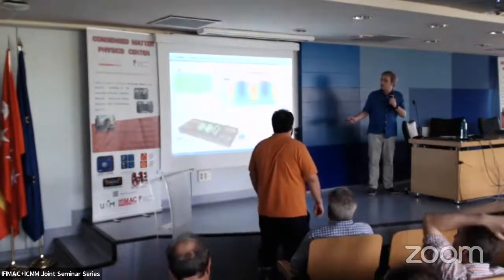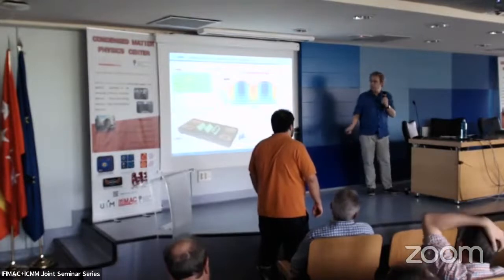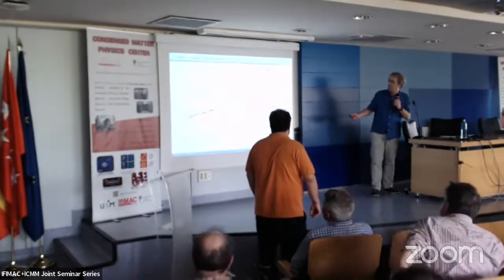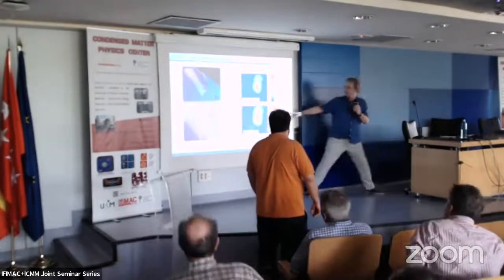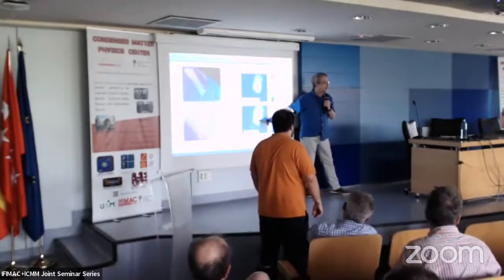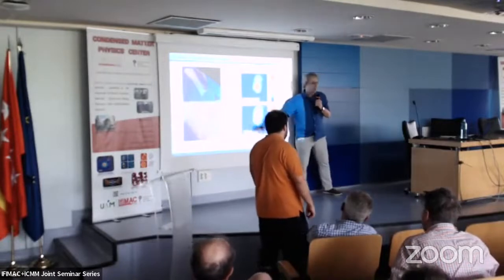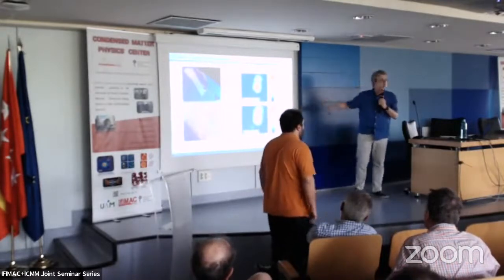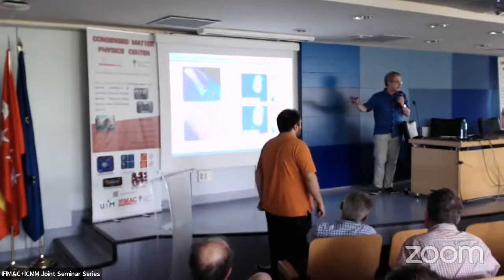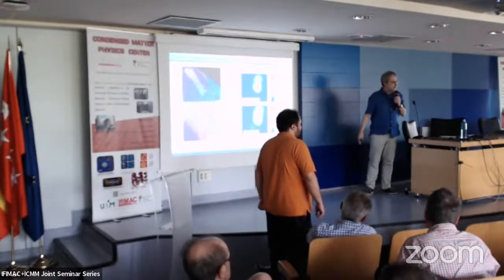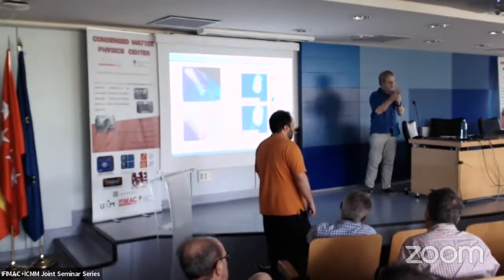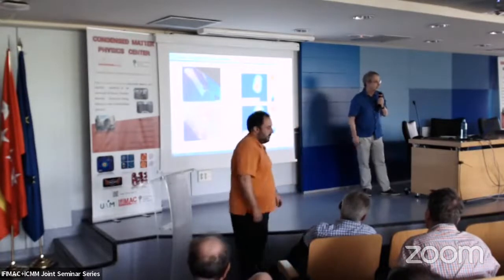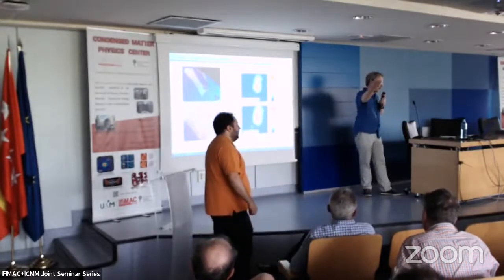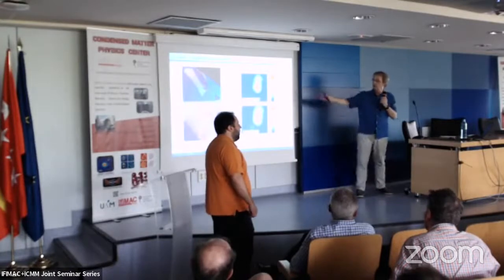Well, we measure this in a spectrometer. It's a micro PL. This is an intensity image, composed of a square grid of 16 by 16 or something like that. But is this process going to excite something? Yes, you just excite with a laser, with a higher energy, and then detect the emission of the material.